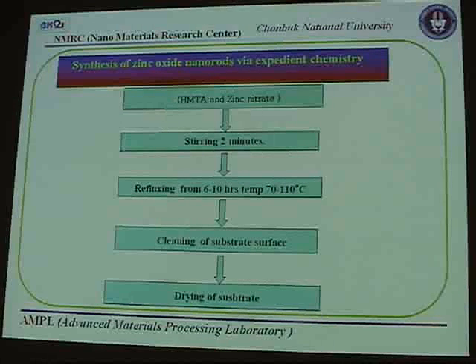This is the experimental method for how we prepare our zinc oxide aligned nanorods: just mix the HMTA with zinc nitrate, stir for some time, and reflux at a temperature between 70 to 110 degrees. Finally, we clean the substrate and dry it.